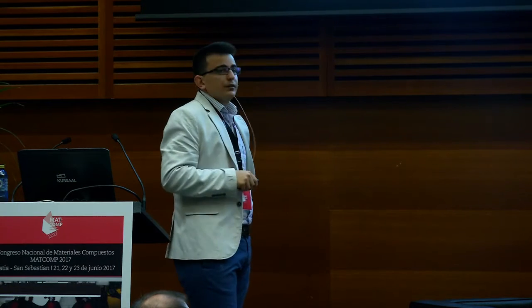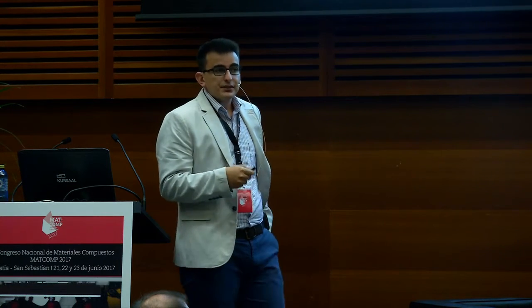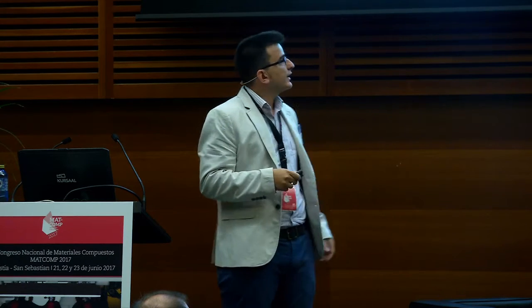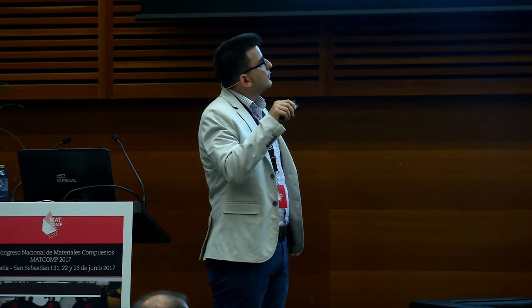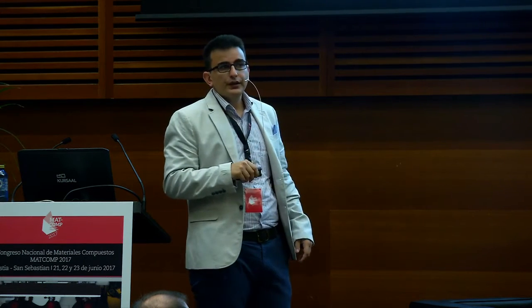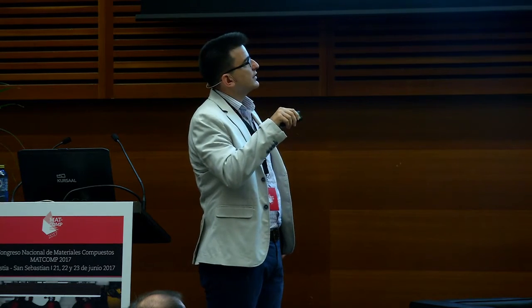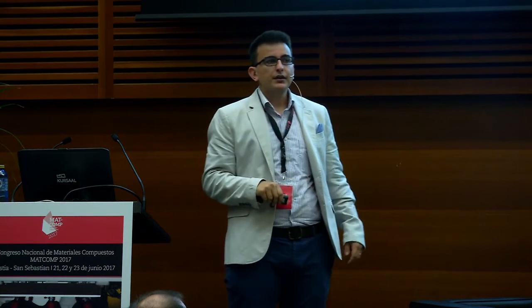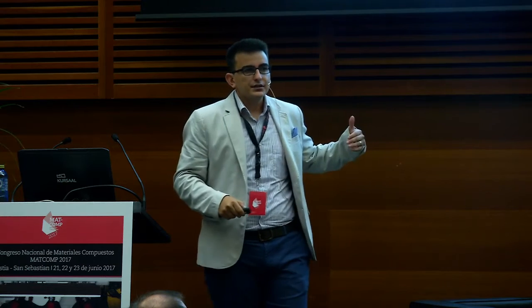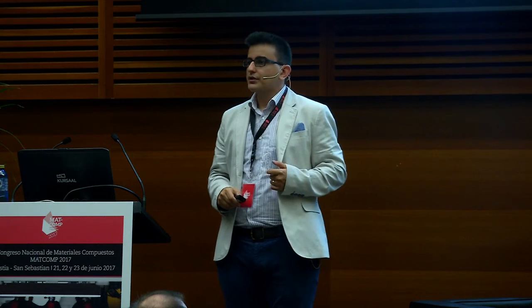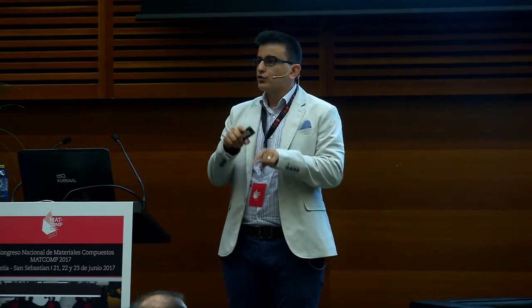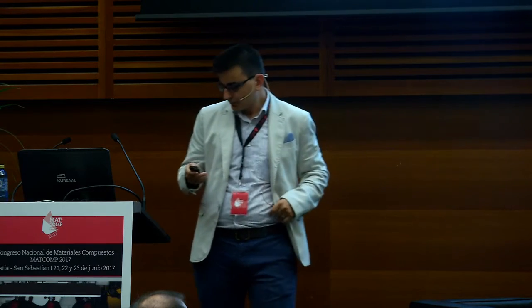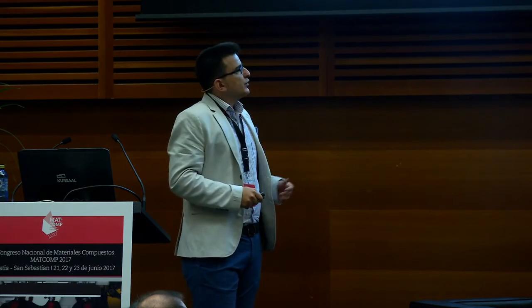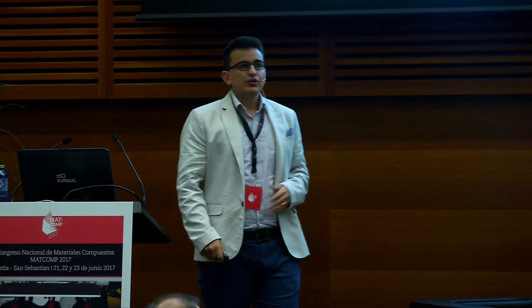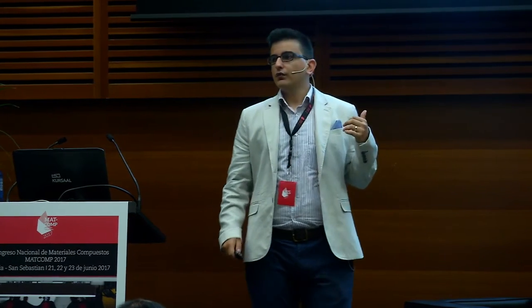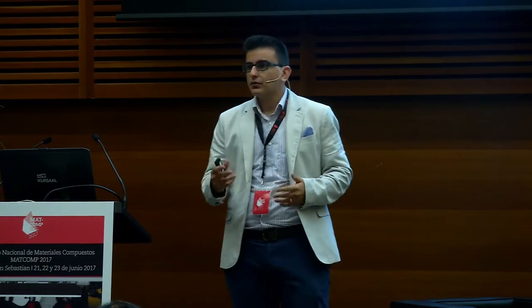And we compare the predicted springback angle with the measured angle from the profiles. And using the process model, we defined springback angle as a function of pulling speed, and it's obvious that the angle is increasing with an increase in pulling speed because of the high through-thickness cure gradients. Similarly, we can predict the warpage in a rectangular hollow profile. So this profile is manufactured using a mandrel.